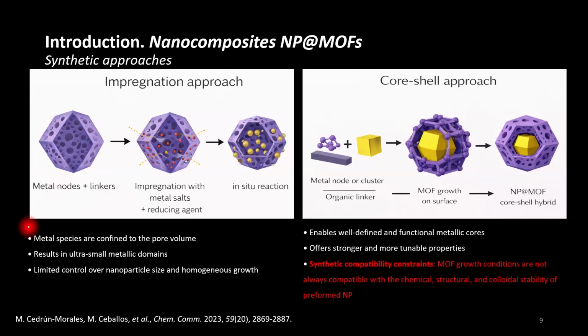And then we decided to go to the core shell approach, that is what I was mentioning before. So it was not trivial at all to do this, because what we found is that the most commonly used synthetic routes to make MOF are not compatible with the stability of metal nanoparticles. Imagine you have a gold nanorod, you make the MOF, and if you find the right conditions, you will make the core shell thing, but you will end up with a sphere coated because you completely deform the conditions. And this is because normally we use DMF, 120 degrees, a lot of time, pressure, acids, and things like that.